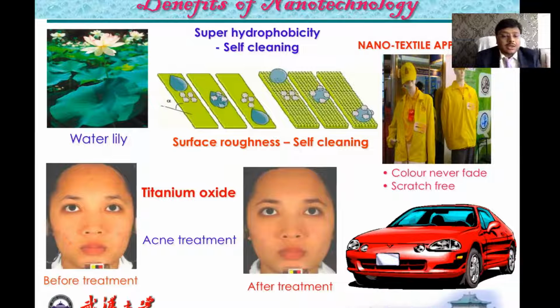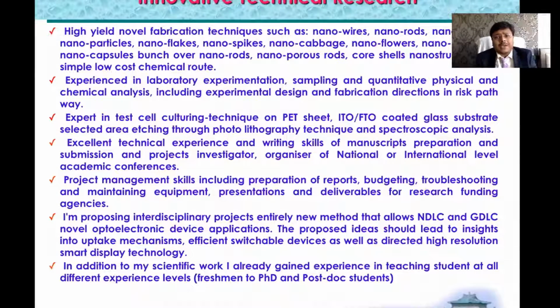You can see here, that's two slides on the screen, how to use the titanium dioxide after treatment and before treatment, how we do that. And my innovative research is basically on nanowires, nanorods, nanoparticles, nanospikes, nanocabbages, nanoflowers, and sometimes we incorporate some hybrid nanorods and porous nanorods, core-shell nanostructures into our host materials.